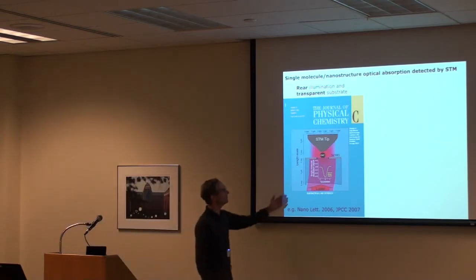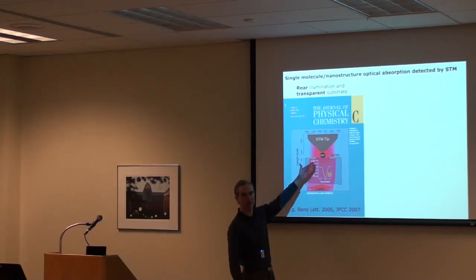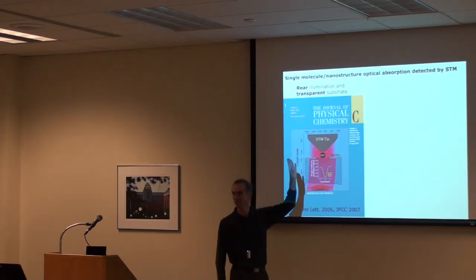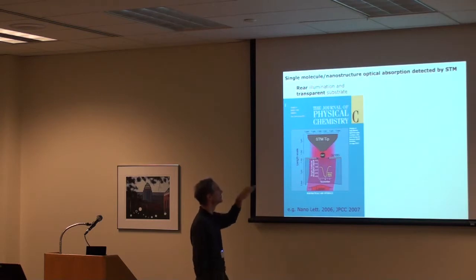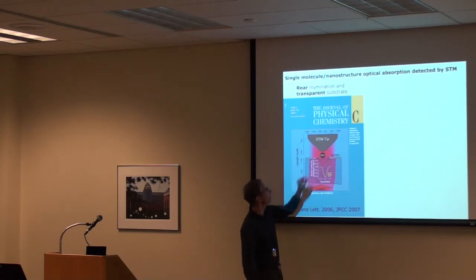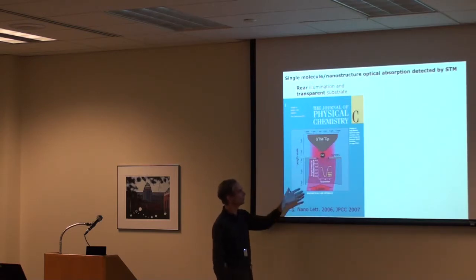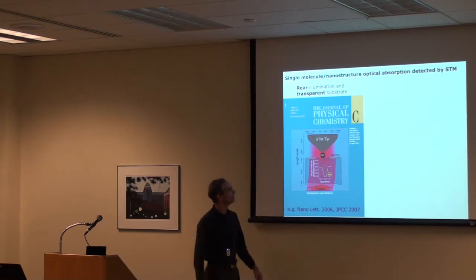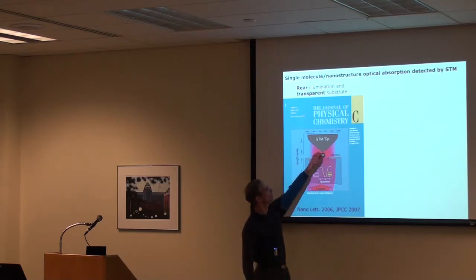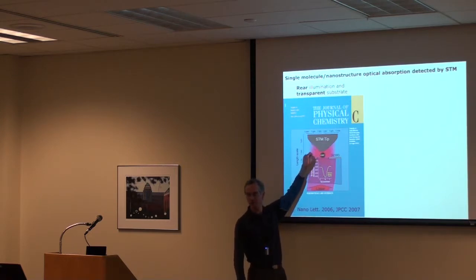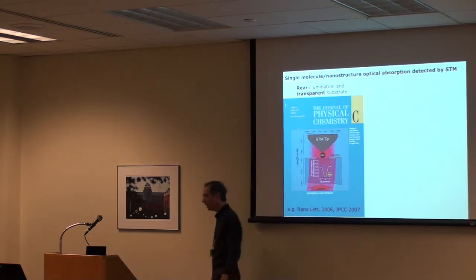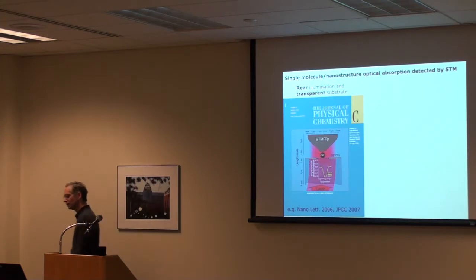Okay, so we send it in total internal reflection from the back, so you only get a half wavelength evanescent wave, and that does much less damage to the signal by heating. Anyway, the molecule is small enough that it's bathed in the laser radiation. And if you put the laser in resonance at the right wavelength, this molecule is going to absorb that light, and its electronic structure is going to change, or it's going to start vibrating, or change in shape. And then you just scan the STM, which looks at the local electronic density of states, and that density of states will change if the molecule changes shape. That's basically what you're looking for in this experiment.